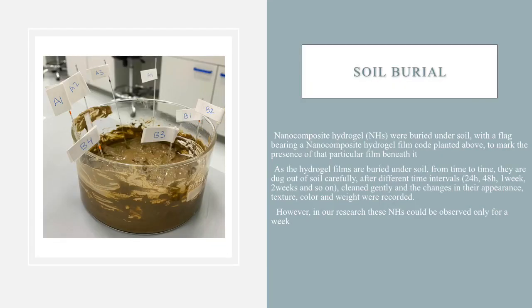And here in the soil burial figure, nanocomposite hydrogels were buried under soil with a flag bearing a nanocomposite hydrogel film code planted above to mark the presence of that particular film beneath it. As the hydrogel films are buried under soil, from time to time they are dug out of the soil carefully after different time intervals, like 24 hours, 48 hours, 1 week, 2 weeks, and so on. They were cleaned gently, and the changes in their appearance, texture, color, and weight were recorded. However, in our research, these nanocomposite hydrogels could be observed only for 1 week.